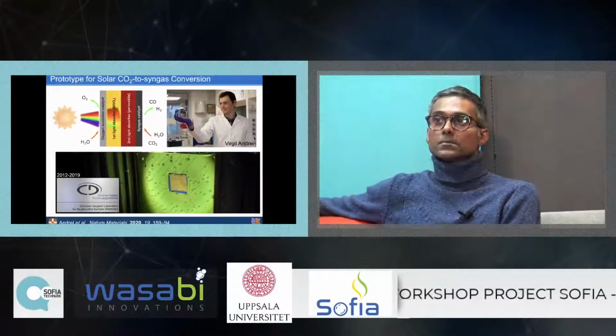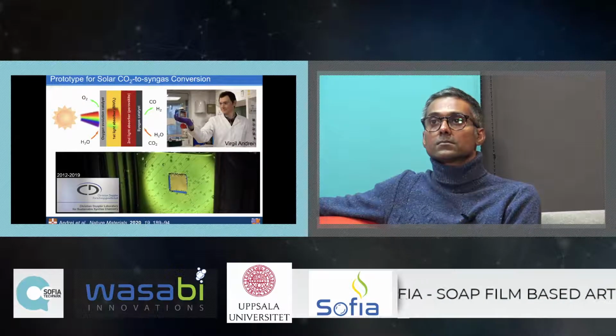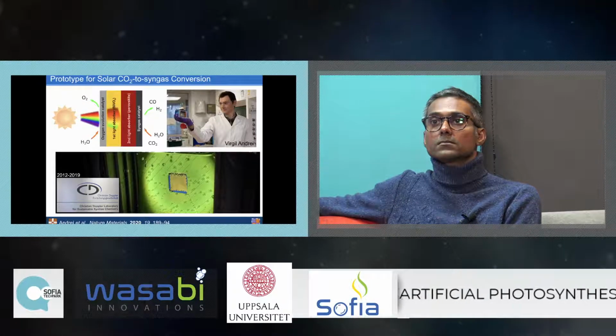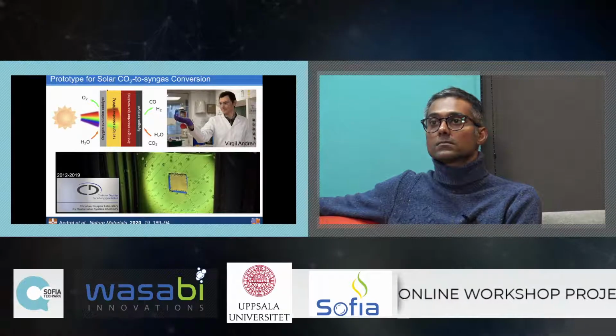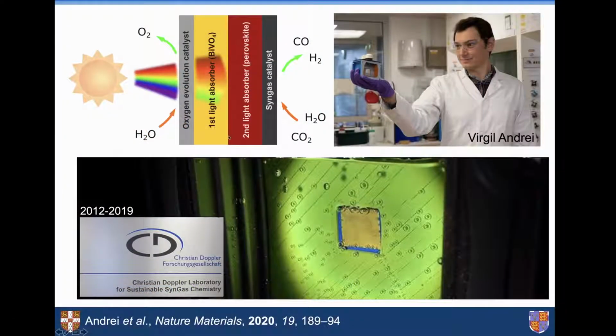So how the system works, it's a tandem system in that it relies on two light absorbers. The first light absorber is a bismuth vanadate photoanode, and the photocathode is a lead halide perovskite element that's commonly employed now in photovoltaic cells. And what we're doing is essentially sandwiching these two semiconductors with two catalysts. One catalyst produces syngas, and the second one is our oxygen evolution catalyst.